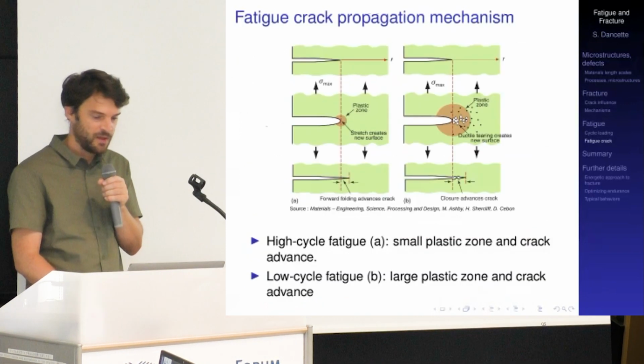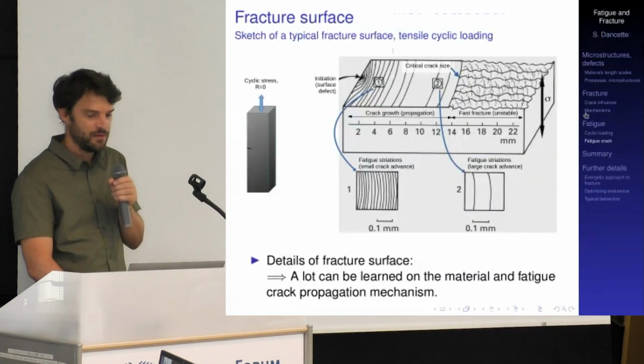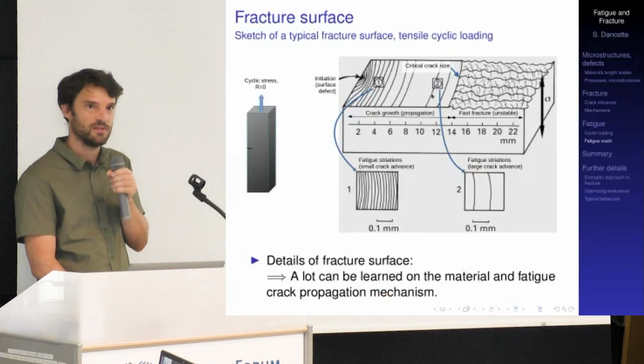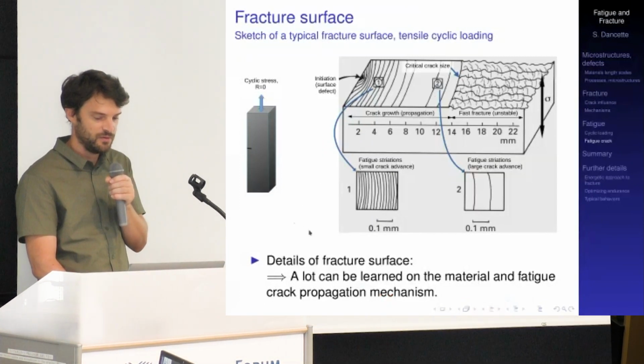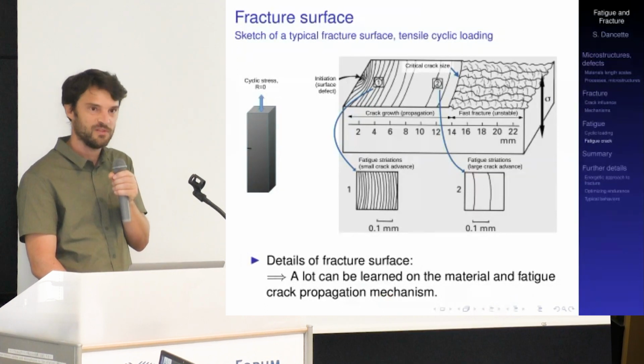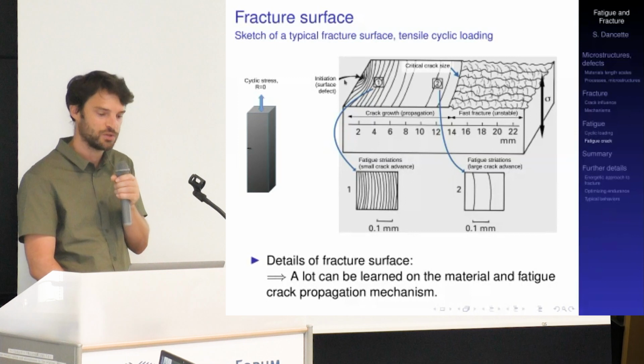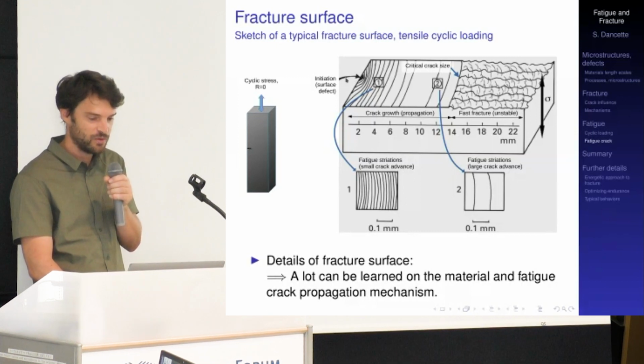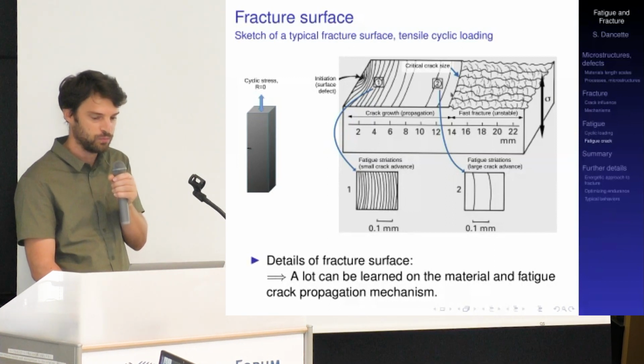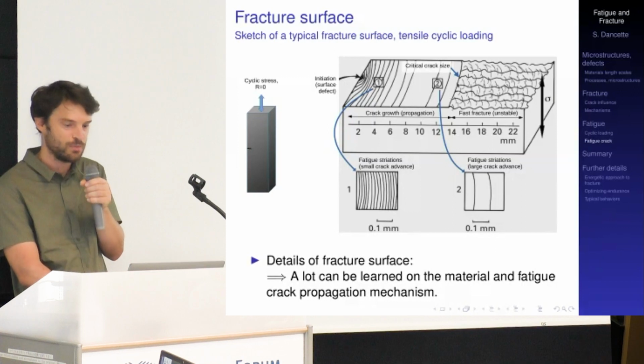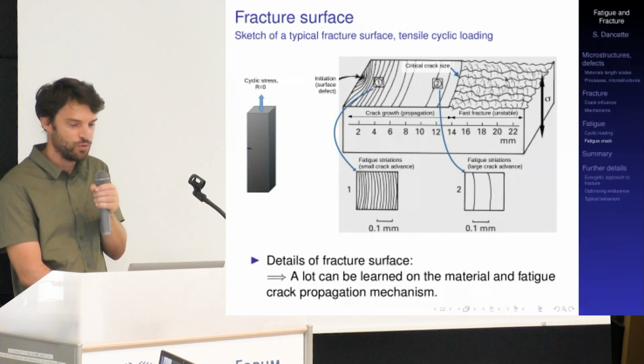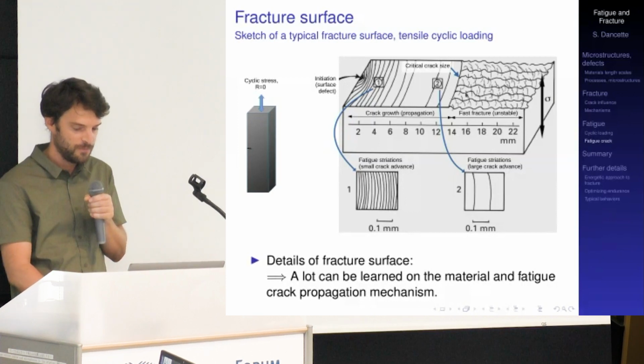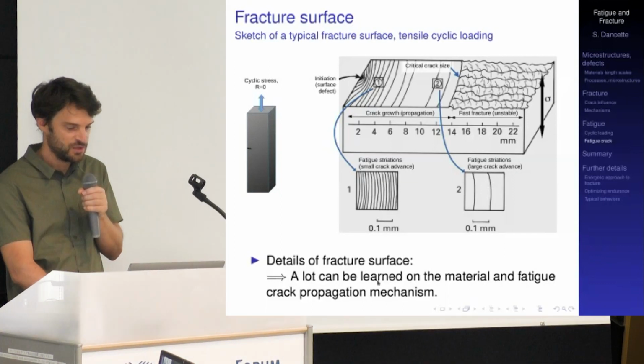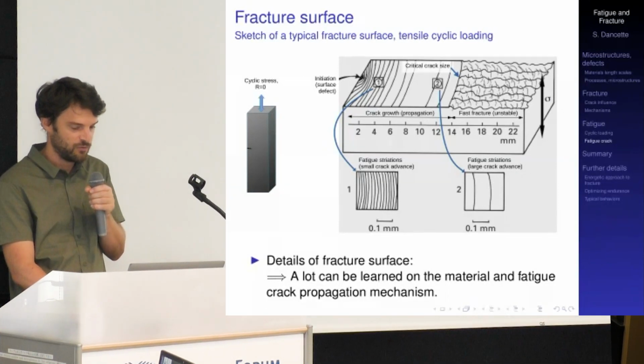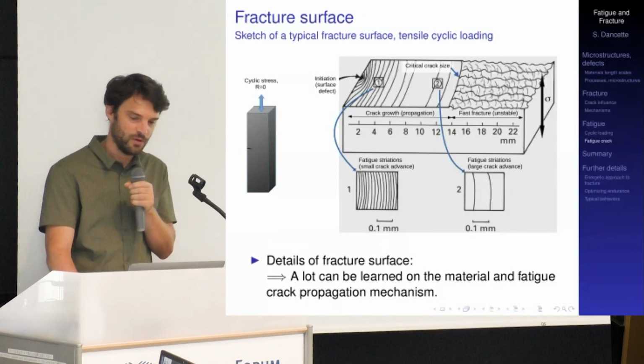the loading process. And if we look at the fracture surface globally, then it offers many details that would allow, for example, the forensic examination of the causes of fracture. It is not unusual to be able to retrieve the initiation site of the fatigue crack, the one that led to fracture, to distinguish on the fracture surface how fast and how long the crack could propagate in a stable way during fatigue crack propagation, and to distinguish in the end the final domain in which fast, catastrophic fracture occurred in the material. So again, last message here: a lot can be learned when you look at the fracture surfaces of materials, even in the case of cyclic loading.